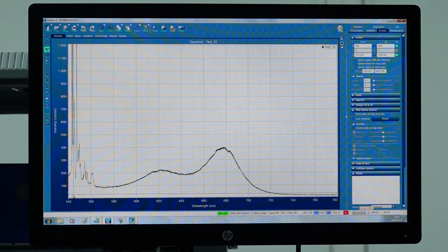You can see a cluster of Raman peaks here which belong to the MoS2 material, that is the material we were investigating, and also the silicon peak. Also with that we can see the PL signal, which is a broad peak. This probably belongs to the direct transition peak for MoS2 and the other is for indirect transition. So using the same Raman setup, we can also observe the PL signal of different materials.